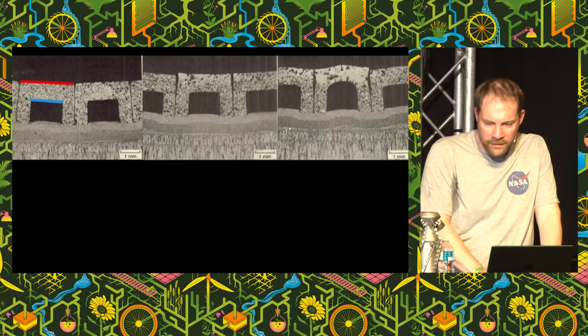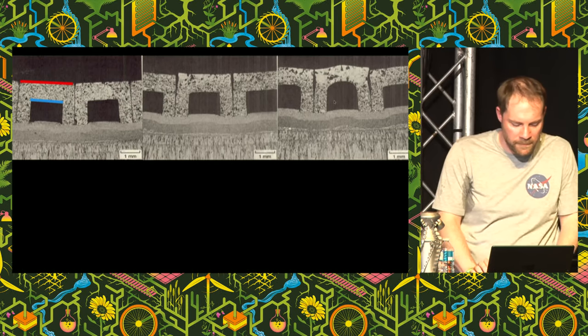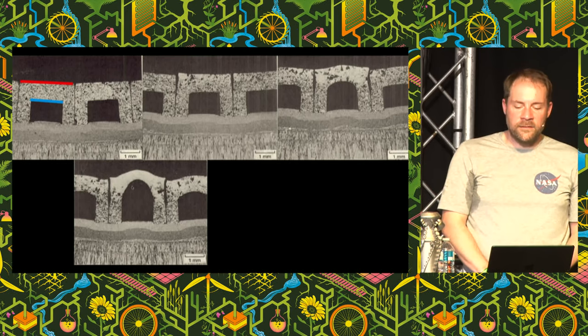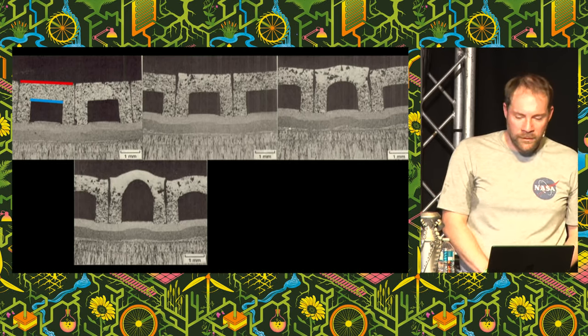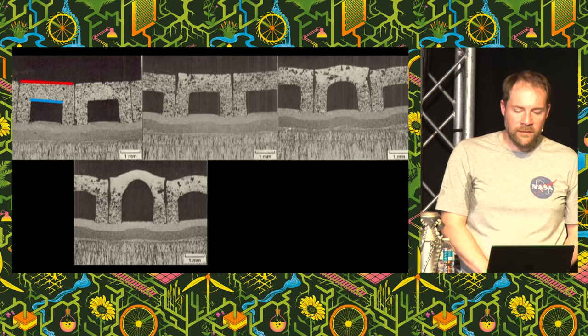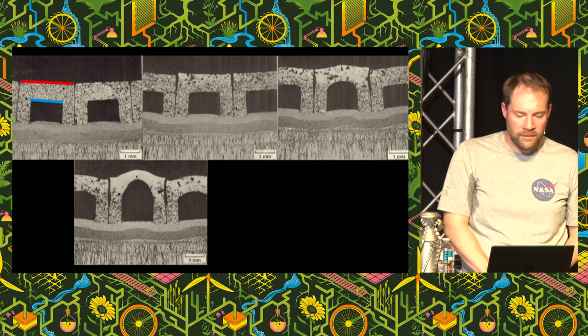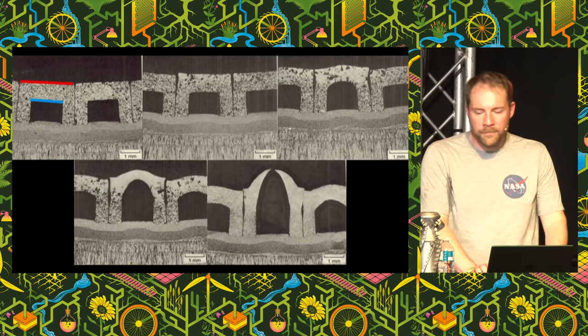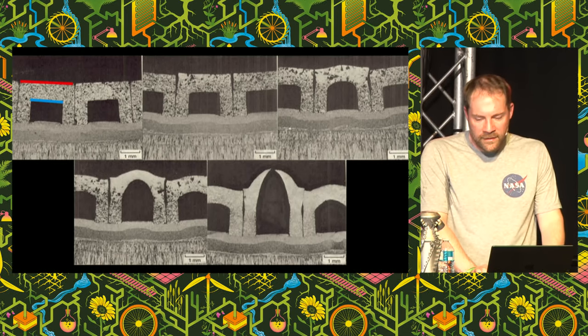And it's bowing out on the inside again because the pressures are wanting to push it that way, because it's higher pressure inside the cooling channel than inside the combustion chamber. It's getting very exaggerated at this point. And interestingly as well, you can see the metallurgy is changing. So instead of lots of little crystals, one big crystal of copper is growing here. That's the downside of using pure copper. It has very good thermal conductivity, but it wants to form big crystals. And then eventually, pop, and the engine is dead. That's a dead engine at that point.